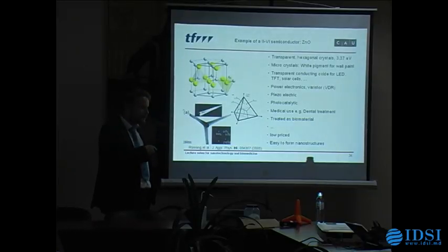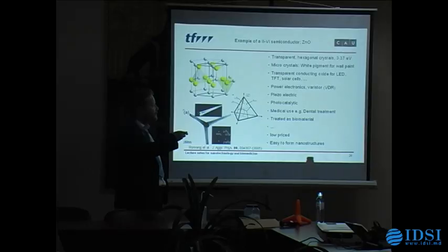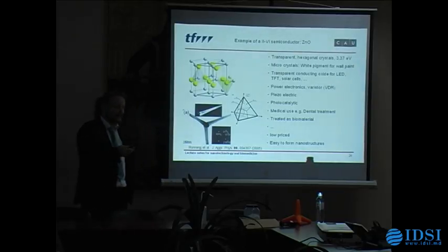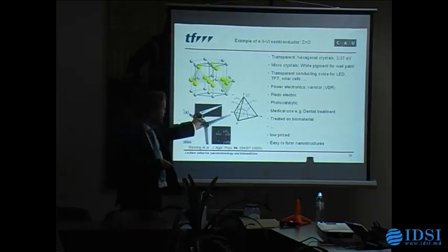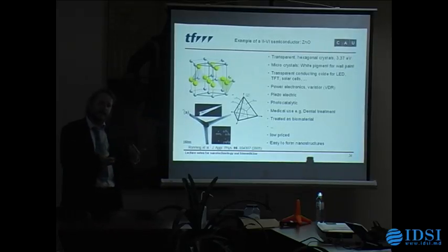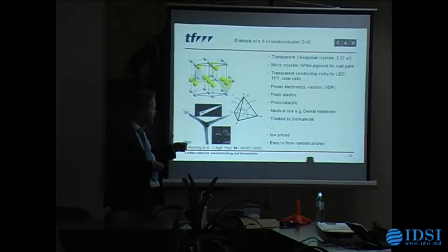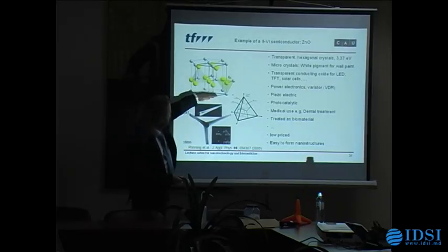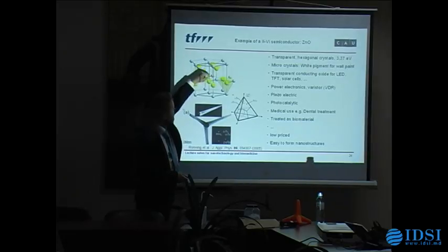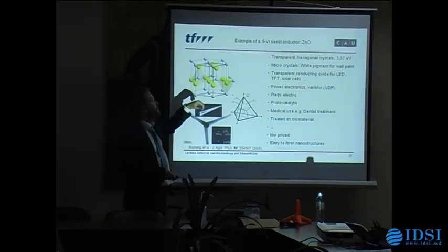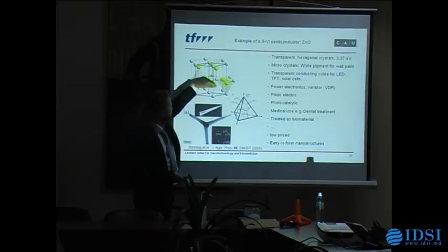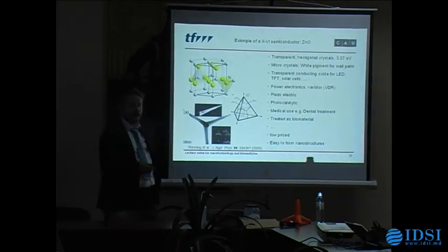But those of you who are from electrical engineering, you could see these are transparent hexagonal crystals with a bandgap of 3.37 electron volts. This is a nice material we use in our group because it's very easy to form nanostructures. This has something to do with the polarity of these crystals. Like water, zinc oxide is very polar, and so therefore, if you're doing some growth process, typically inside of the crystal it shoots up in one direction. This direction is the wurtzite crystal system, so it's the 0001 direction, the C-axis, where it grows very fast, and these other sides are growing very slowly.